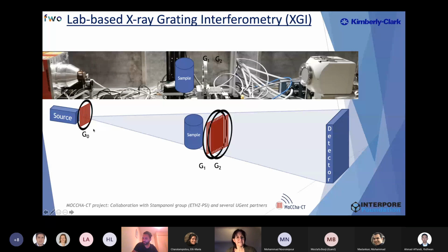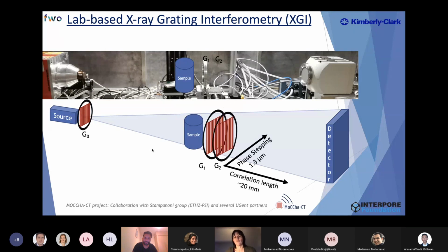The idea is that if you have a standard CT system with a source, sample, and detector, we now apply gratings — gratings that can change parallel to each other and also perpendicular to each other. By playing with those gratings, we get different signals in our detector.